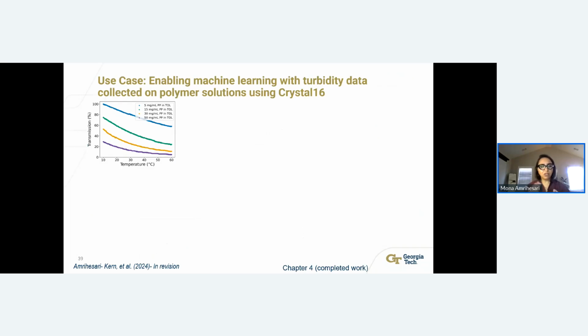So now that we talked about how we standardize the method, we standardize our method to 900 RPM, going through 2 cycles of heating and cooling, and heating and cooling ramp rate were kept at 0.5 degrees C per minute. Let's look at some of the use cases, how we use this data that we collected in a high throughput manner, and how this data is useful.